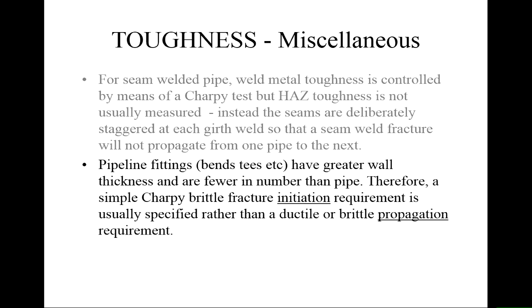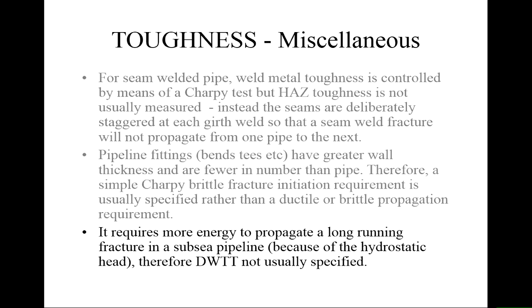In fact, some people assume that a fitting with a heavier wall thickness will stop the crack propagation because the stresses will drop in that anyway. So they're almost put in as crack arresters every now and again. The Charpy test, though, is there because of the material quality, and we want to make sure the sulfur contents are reasonable and things like that.